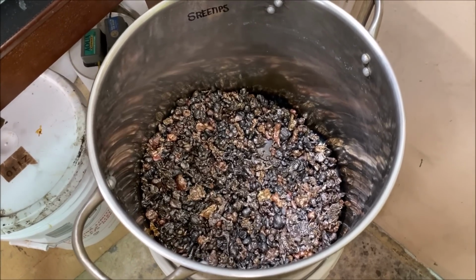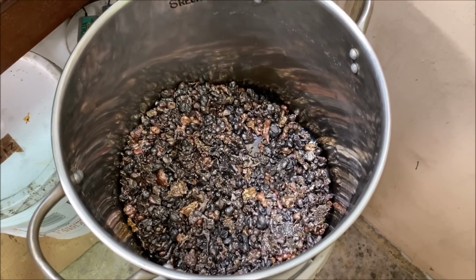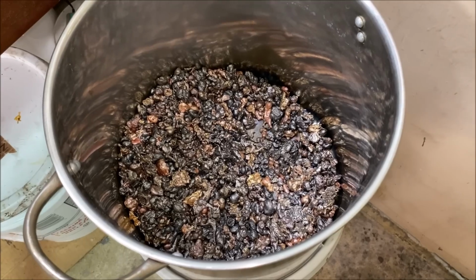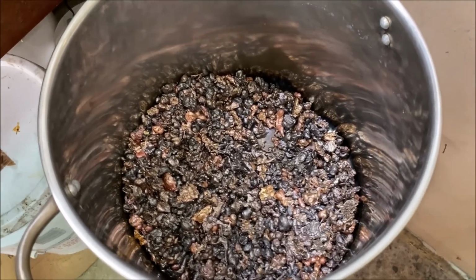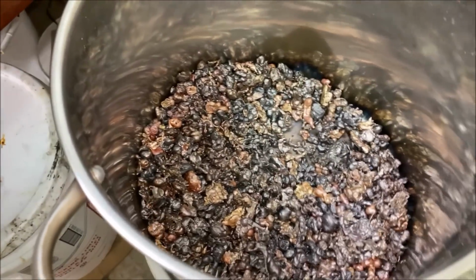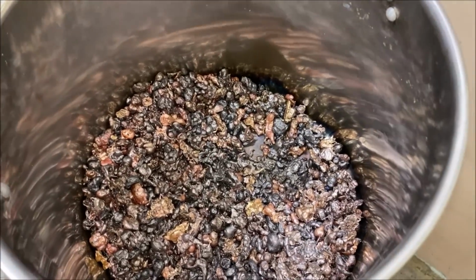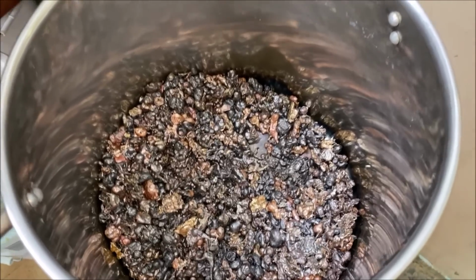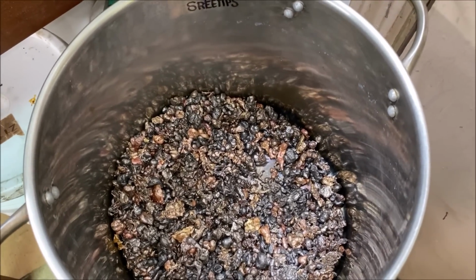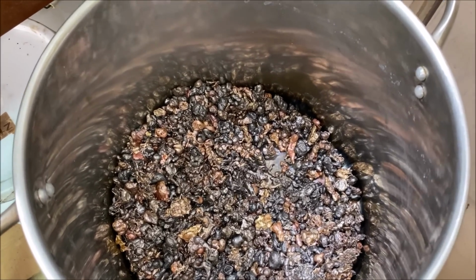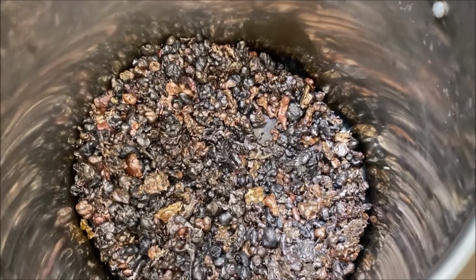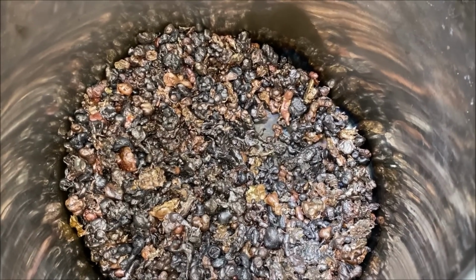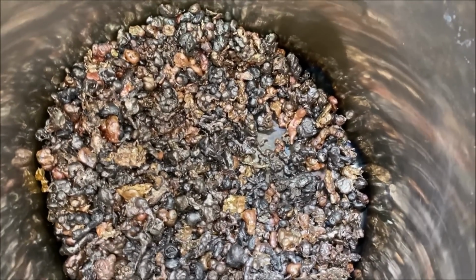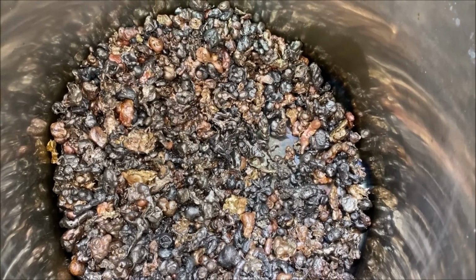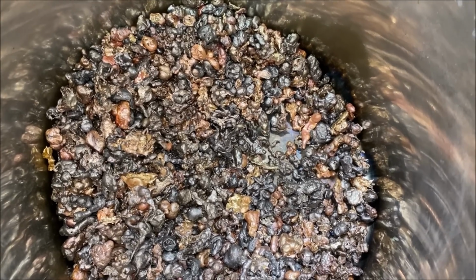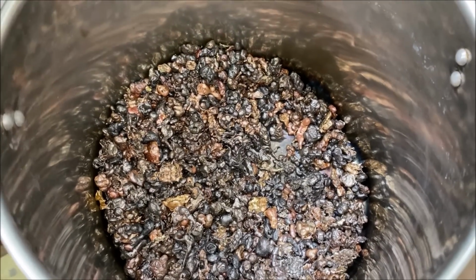That silver powder in my 5-gallon bucket that I used copper to cement the silver out, I gather up the silver powder in the bottom of that bucket, and I rinse all the blue liquid off of it. The blue liquid is copper nitrate, and then I melt it into these granules. Copper will be the main contaminant here, and that's why it looks so ugly.